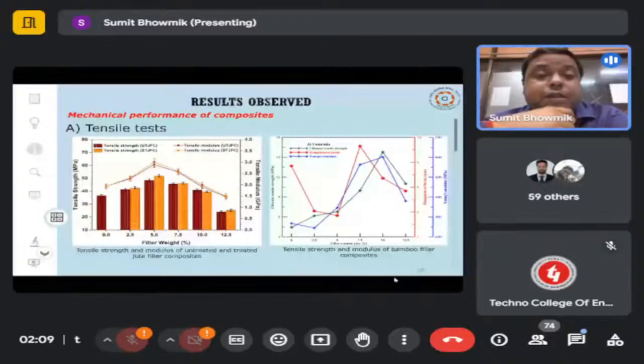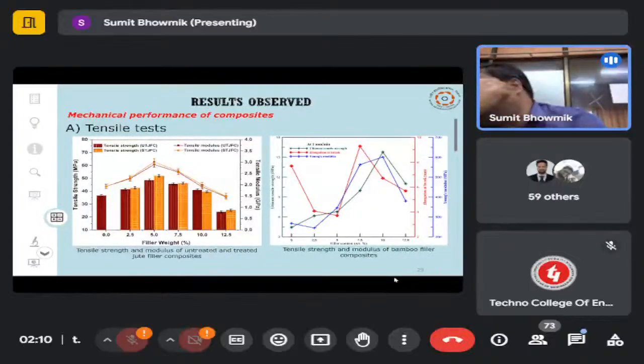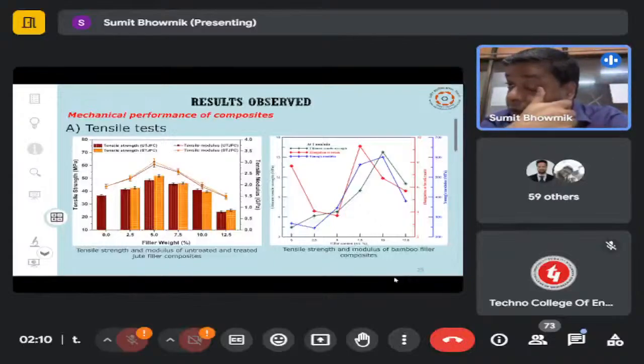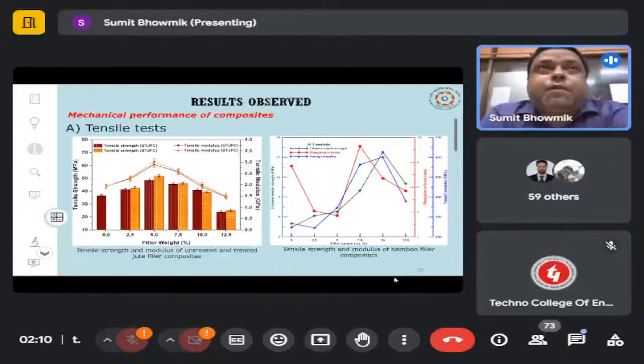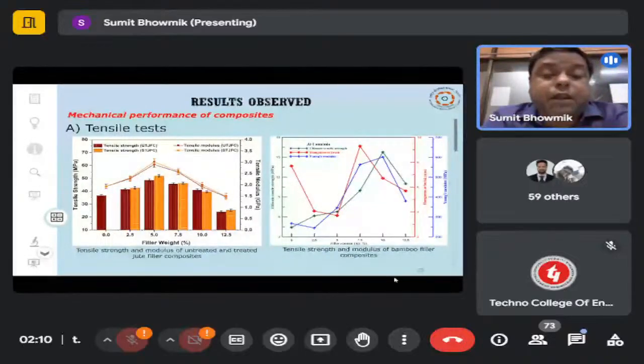Okay, so next, some results have been represented for different materials. To prepare the samples, we first made the filler content 0%, that is, only epoxy. Then samples were also prepared by increasing the filler percentage in the epoxy resin, like 2.5, 5, 7.5, 10 and 12.5 percent filler content. It has been observed that for most properties, whether physical or mechanical, with increasing filler content up to 7.5%, in some properties 2.5%, in some cases 5% or in some cases 7.5% filler content, the best property has been found, whether it is tensile, flexural, modulus, tribological, or some other case.